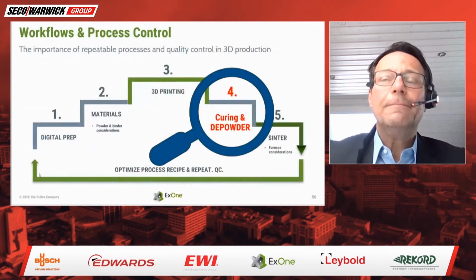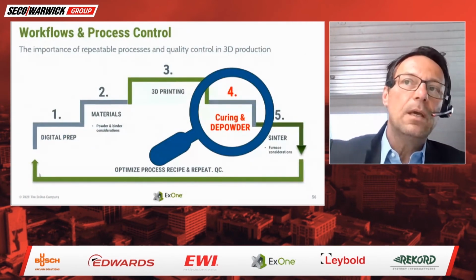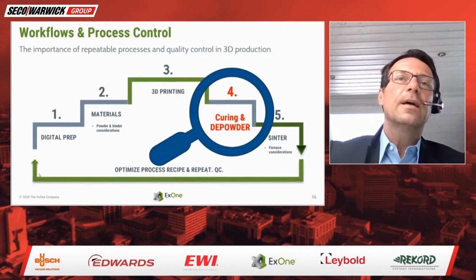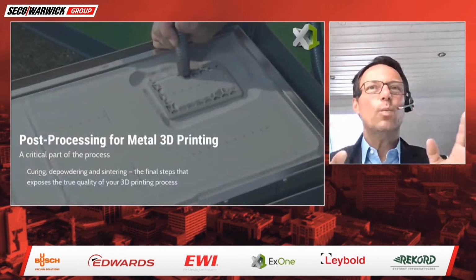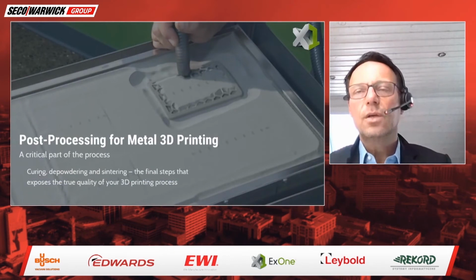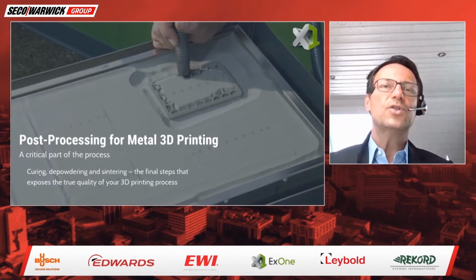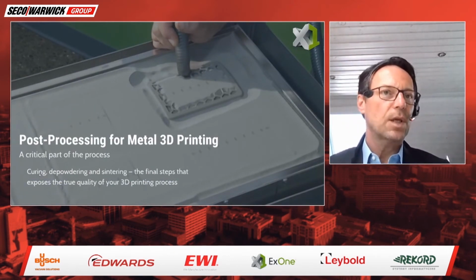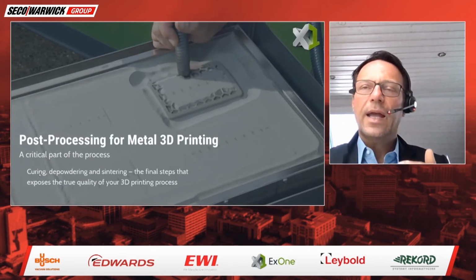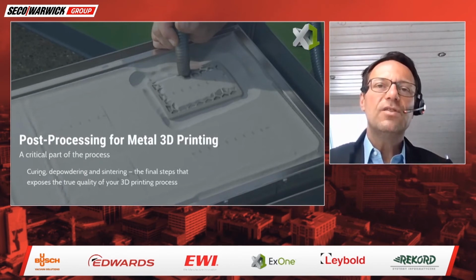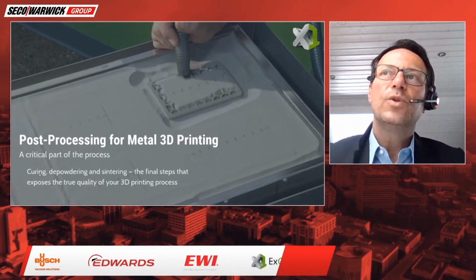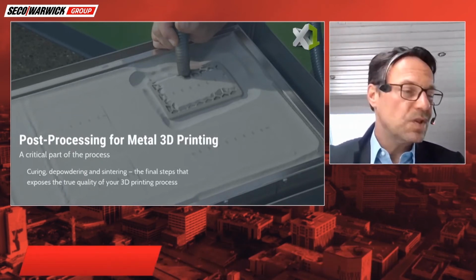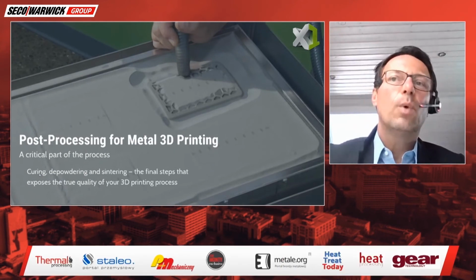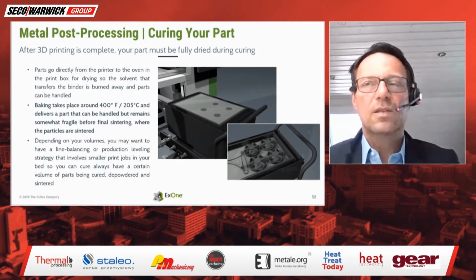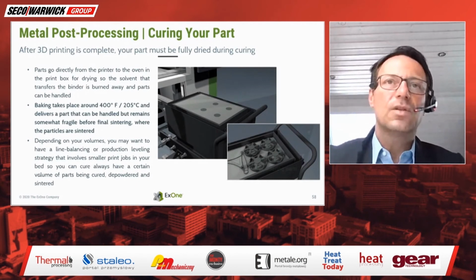Curing. And now it's going to be curing and sintering. You can do binder jetting, but without the depowdering, the curing, and the sintering step, the binder jetting green part means nothing. So you need to post-process. You need to debind and depowder and then sinter the green part which we have printed. It's important to understand that this belongs together. One thing is printing, the other thing is the depowdering and the sinter step.